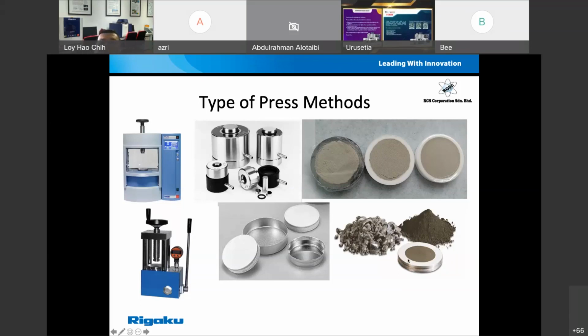Okay, and sometimes we also can use aluminum cups as our backing material. So it means you put your samples in the aluminum cups, then you load it in the pellet die, then you press it, then it becomes a pellet. The good thing about using aluminum cups or steel rings is that this will prolong the life of your pellets, meaning your press pellet will not easily break or fall apart during the process.